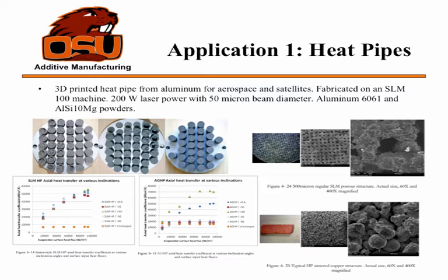So they 3D printed these out of aluminum, both AlSi10Mg and aluminum 6061. They used an SLM 100 machine, 200 watt laser power and 50 micron beam diameter, and they varied exposure times and other things like that. They did quite an extensive parametric study to find out what's stable. You can see a couple of build plates there where they were varying parameters to find out how to get a porous, stable structure. And you can see some of those obviously failed.